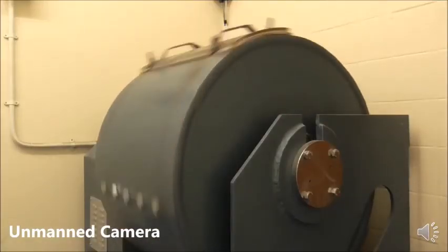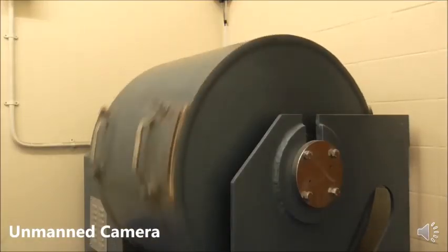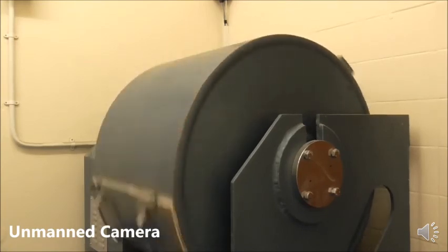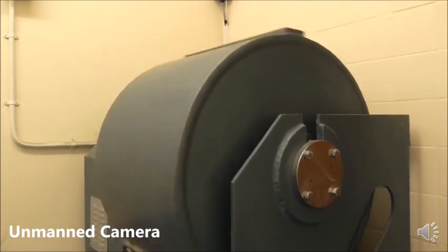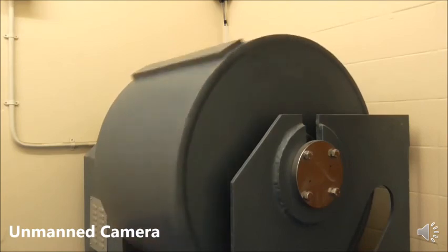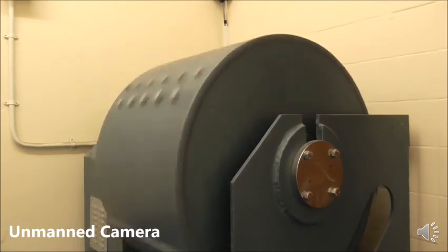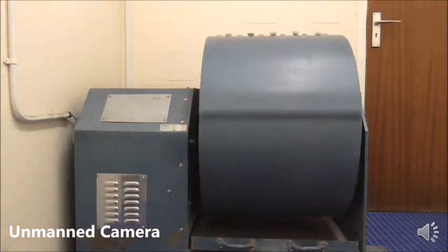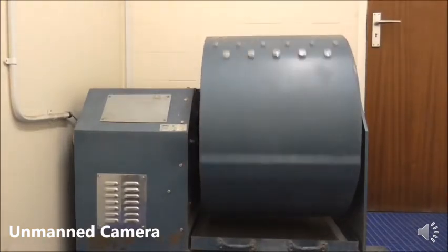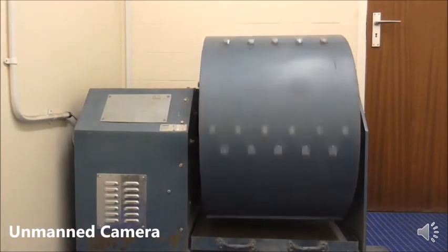They turn it on, and what they're doing is they're spinning it, and it will be spinning for 500 revolutions. Very noisy, this. Each ball must have a diameter of between 45 and 49 millimeters and a mass of between 400 and 445 grams.